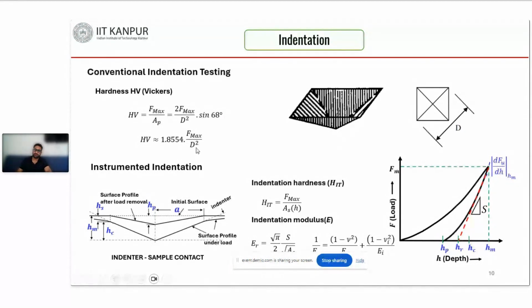Although this conventional indentation testing was good, for a very small load the impression is very small, so it cannot be measured well from the optical microscope, and if you try to measure it, it will give a little bit of error. Also during the unloading there is a recovery in the impression, which leads to a minor error in the hardness value. And also this conventional indentation technique does not give the modulus value.